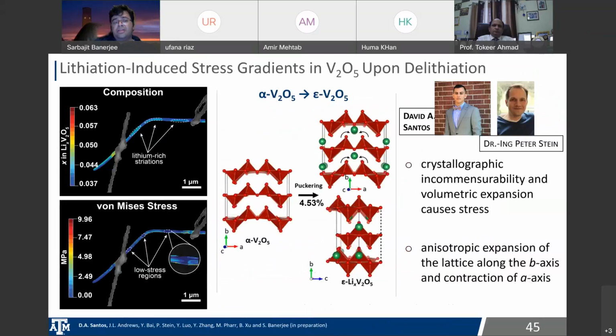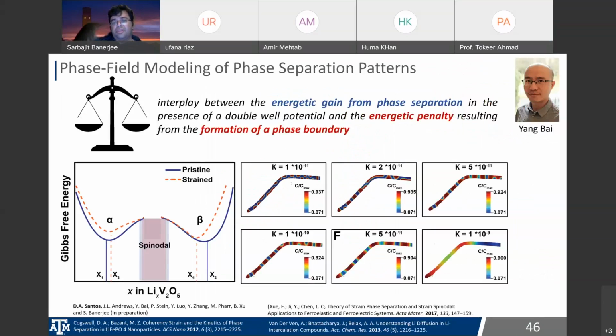So fundamentally, when lithium ions intercalate, you have a choice of having a single phase with no phase boundaries, or, if the penalty for the phase boundary is not too high, you can introduce a series of phase boundaries and instead have phase separation. So kappa here is a measure of the approximate penalty that you pay for that boundary, which has to do with the elastic misfit between the two phases, and we can match the simulations to the experiments and figure out the regime we are in in terms of kappa that allows us to see these striations.